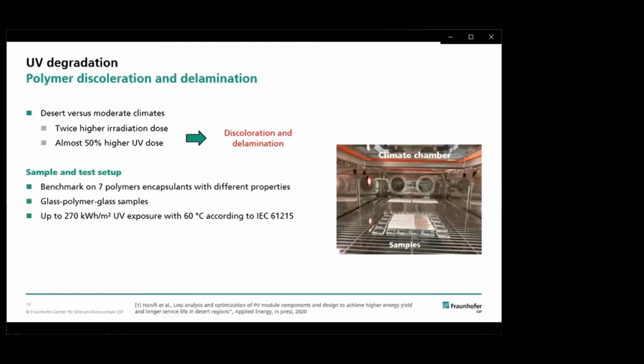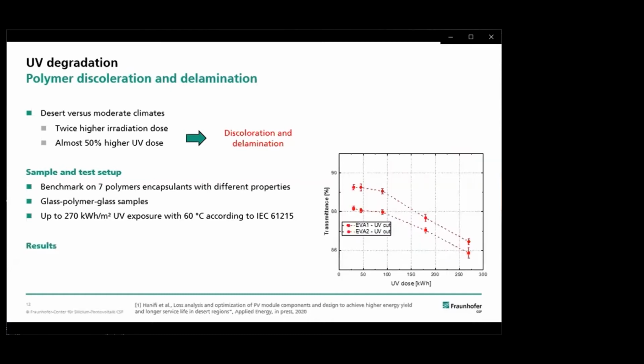In order to see the impact of UV degradation on different materials, we did a benchmark test on 7 polymers, which were used for encapsulation and had different properties. From those, we prepared glass-polymer-glass samples and exposed them to UV of up to 270 kilowatt-hour per square meter at 60 degrees Celsius, according to the IEC 61215. And here you can see some results, some optical results. First, to see how the transmittance changes, and with the transmittance also directly connected, the PV output will change. And here we had some EVA with UV cut properties, which degraded by 2% after the 270 kilowatt hours per square meter.